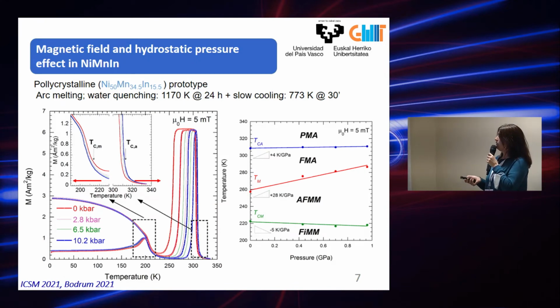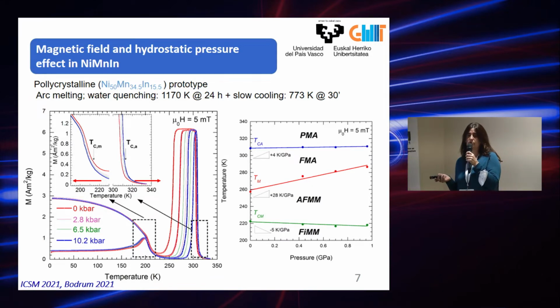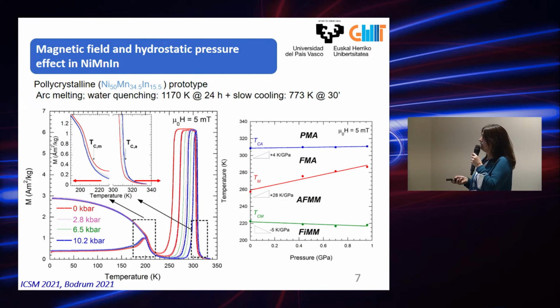For this, we use a polycrystalline nickel-manganese-indium, which is a prototype, and we are measuring different magnetization curves at different pressures. It is very clear that we have here our structural transition, but also we have two magnetic transitions, in the austenitic phase and in the martensitic one. As we expected, the pressure increases the transformation temperature, but the impact is different in the magnetic transition.